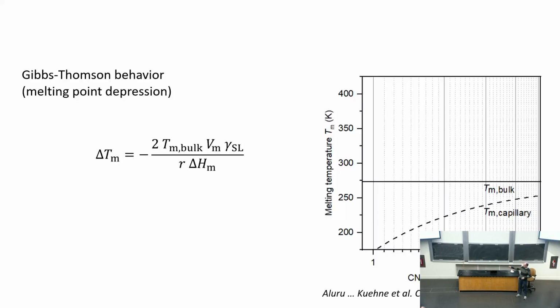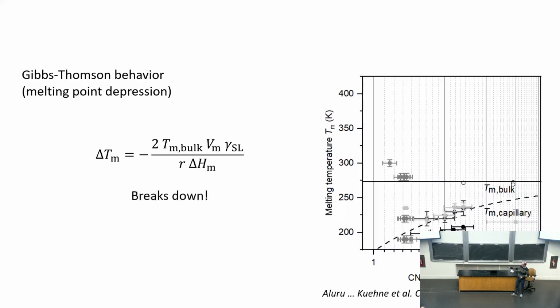If you think about water, the bulk melting point is what you all know, 0 degrees Celsius. When you put water in smaller and smaller pores, this melting point is predicted to decrease just because of the increased importance of interaction with the wall and the radius that comes in here. So this is the bulk, continuum prediction, and it actually matches experiment pretty well, down to about 1.5 nanometers. These are all from X-ray diffraction studies done in the early 2000s. At about 1.5 nanometers, you see this deviation. So Gibbs-Thompson behavior breaks down.